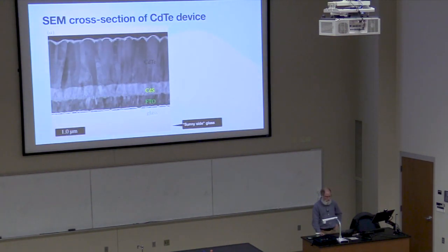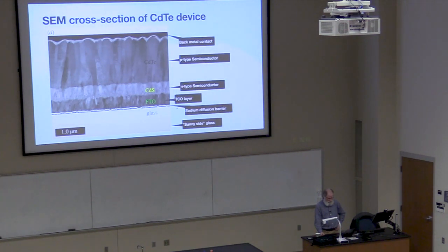So here's a cross-section of a device. Here's the glass. This glass is about 3 millimeters thick, so we're only showing the very top of the surface. And then here are the layers. Here's the transparent conductive oxide layer, the first semiconductor layer, the next semiconductor layer, and I'll be honest, I'm not fully sure what was above this. I'm guessing this is the back metal contact. There may have been some other steps just to prepare this for the electron microscope, but we'll assume that's what it is.